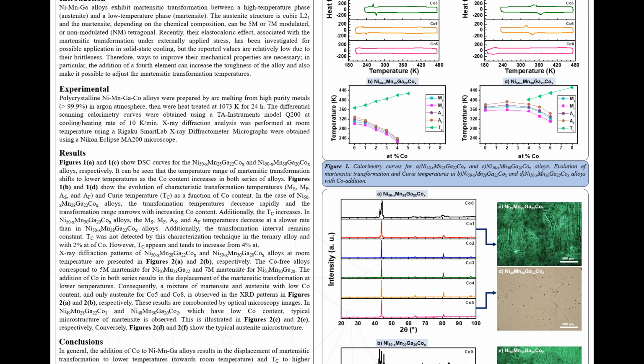In the case of Ni50-xMn25Ga25Cox alloys, the transformation temperature decreases rapidly and the transformation range narrows with increasing cobalt content. Additionally, the Tc increases. In Ni50-xMn30Ga20Cox alloys, the MS, MF, AS, and AF temperatures decrease at a slower rate than in the prior alloys. Additionally, the transformation interval remains constant. Tc was not detected by this characterization technique in the ternary alloy and with 2% atomic of cobalt. However, Tc appears and tends to increase from 4% atomic.